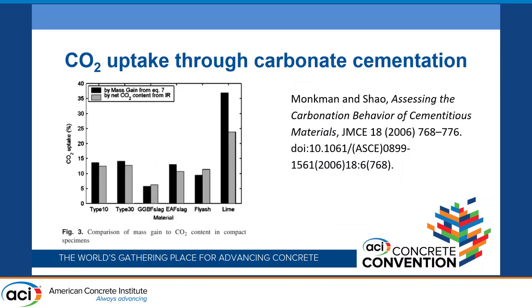This is some work I did looking at a number of different materials, treating them with CO2 and comparing how much CO2 goes in. In the same sample I measured it with the infrared sensor versus TGA. This was a quasi-closed system, and we saw some generally good agreement with the exception of hydroxide.